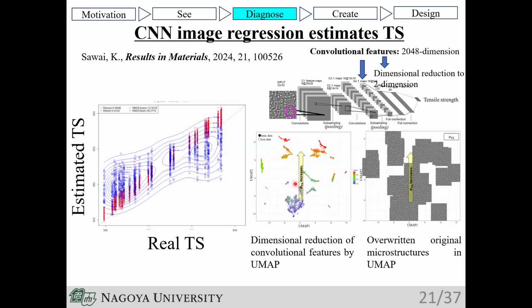to greater tensile strength. To facilitate human interpretation of these features, the original microstructure images have been overlaid onto the plot. From the visualizations, one can observe a tendency of higher tensile strength as the second phase becomes more finely dispersed. So from these dimensional reductions, human beings can understand how the computer finds the important descriptors in the CNN image regression models.